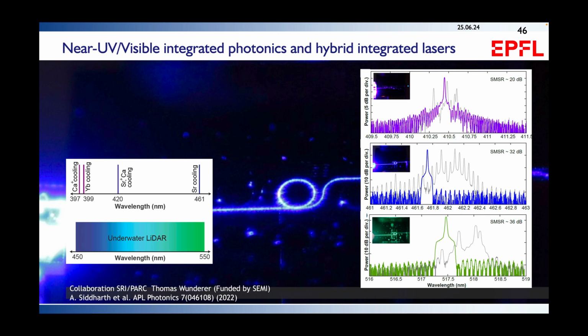Now last, silicon nitride is transparent down to the visible. In fact, the lowest wavelength we have shown is 369 nanometers, together with Park Semiconductors, now called SRI, Thomas Wunderer. Other wavelengths we have shown are 410, 461, 517. So you can really see that these circuits can not only generate frequency agile lasers at 1550, but also be used to create very compact lasers that can, for instance, be used to stabilize optical atomic clocks or for repumpers in a compact form factor.